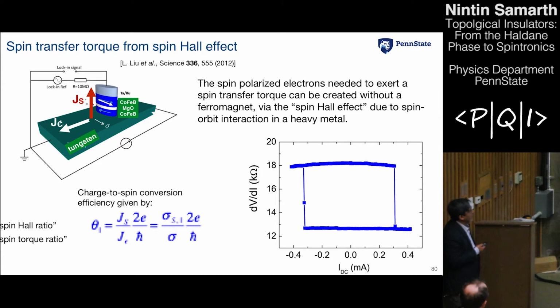So one of the ideas that Dan Ralph and his group demonstrated some years ago was that if you take a metal like tungsten, so tungsten is something that has a strong spin-orbit coupling because it's a heavy element, and you flow a current in tungsten, then what happens is that because of a phenomenon known as the spin Hall effect, you get a spin current which is generated in an orthogonal direction. Okay? So you flow a charge current over here, but you get spin polarized electrons going this way.